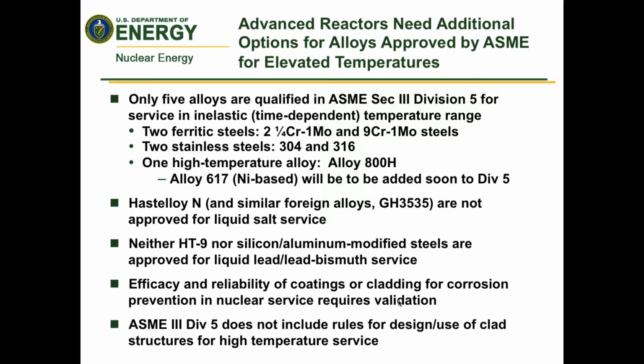Some of the other alloys which people have identified as useful and desirable for these other reactor systems, such as Hastelloy N for liquid salt service, very good, very little corrosion up to 700 degrees C, which is about the temperature at which it loses strength, would be great. Similarly, the Chinese equivalent, the GH3535 that's being developed at SINAP, are not approved by the code for high temperature nuclear construction. Similarly, HT9 and the silicon aluminum modified steels, which people are looking at for lead and lead bismuth service, they're just not in the code. You cannot use those for nuclear construction at this point in time.